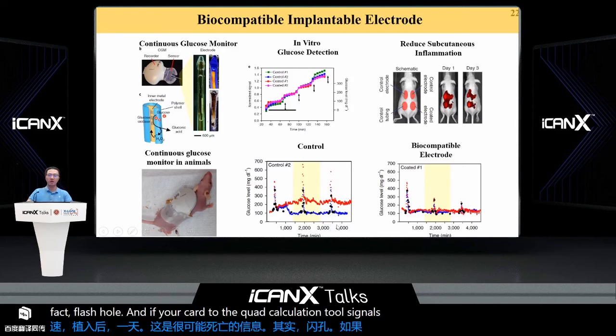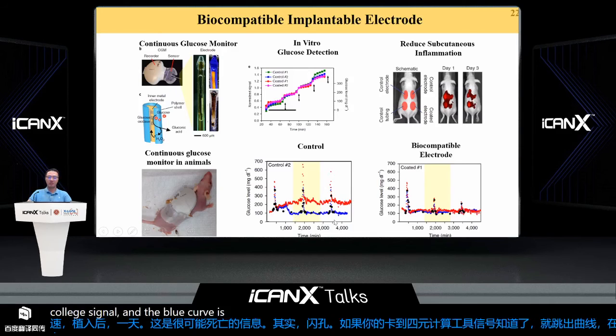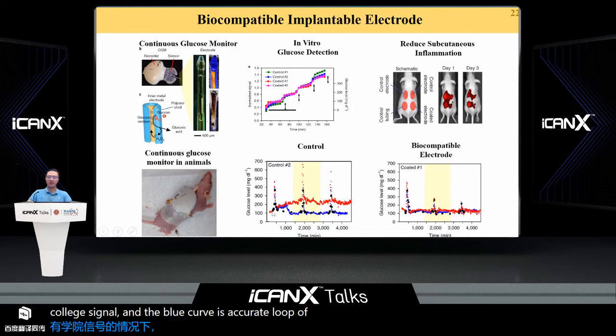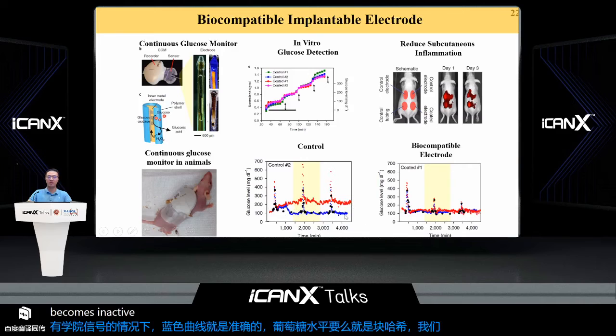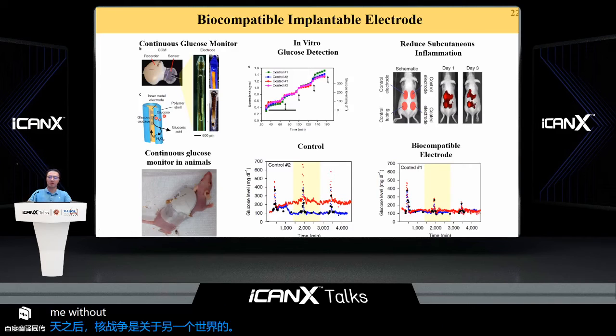So here, as the result shows, the red curve indicates the recorded signal, and the blue curve is the accurate glucose level that is calibrated by the blood test. We can see that the signal becomes inaccurate quickly after one day. If the electrode was coated with our biocompatible polymer, the sensor could record the glucose accurately without calibration.